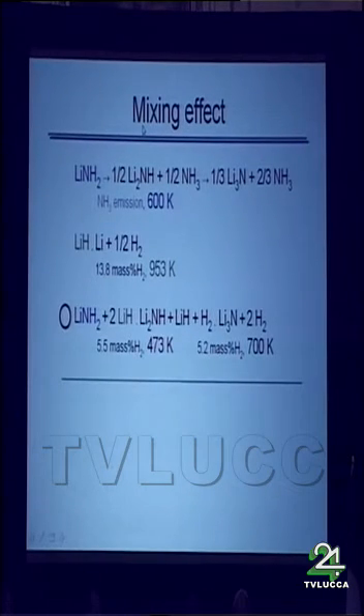I'm now very interested in the mixing effect. In case of lithium amide, it decomposes into lithium imide or nitride, as Dr. Chen explained, around 600 Kelvin. But also lithium hydride changes into lithium and hydrogen. In this case, the dehydriding reaction occurs at more than 900 Kelvin. But just by mixing, the decomposition or dehydriding temperature is reduced so much, like this. This is a mixing effect, but it does not always happen.